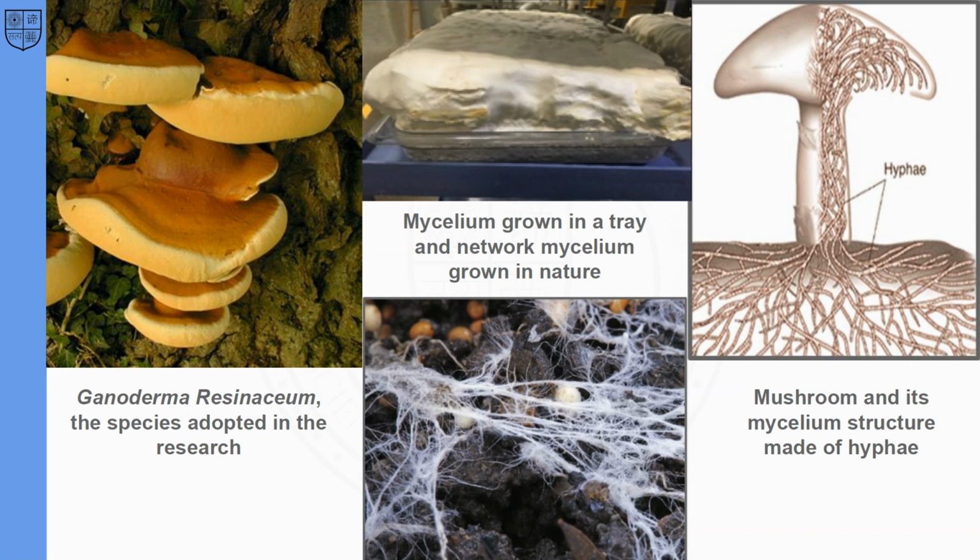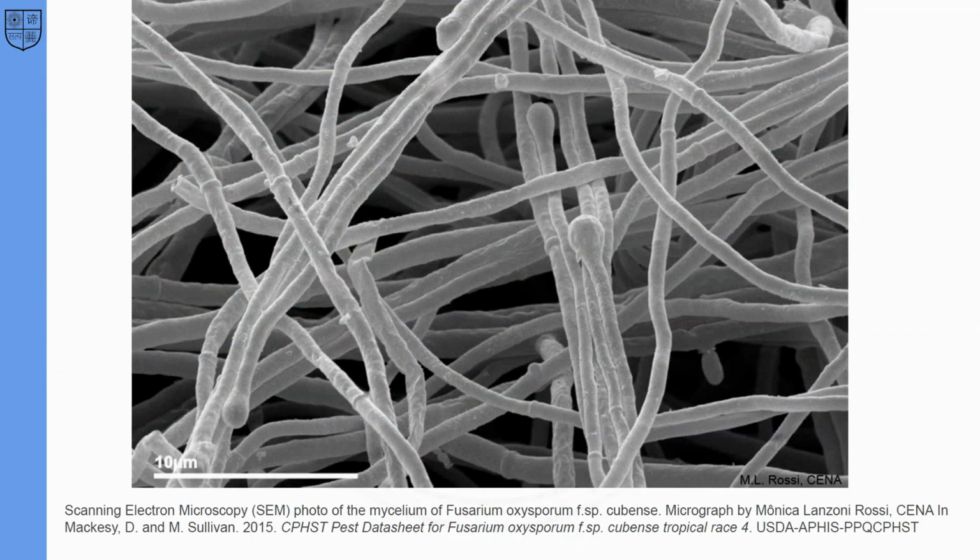Mycelium consists of microfibers made of biopolymers such as lipids, chitin, and glycoproteins. It can be used as a programmable biomaterial, substituting styrofoam in packaging, as leather, as architectural materials, and even food. The porous nature of the mycelium creates a mesh that resembles an open cell foam structure. Being a natural microporous material, mycelium has great potential for applications in high-performance filtration membranes.